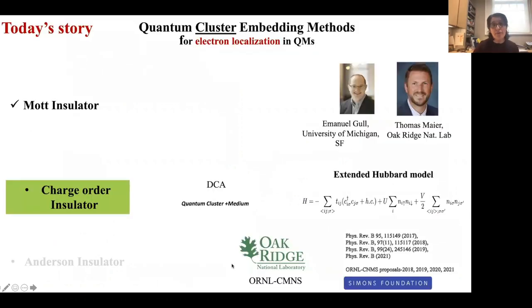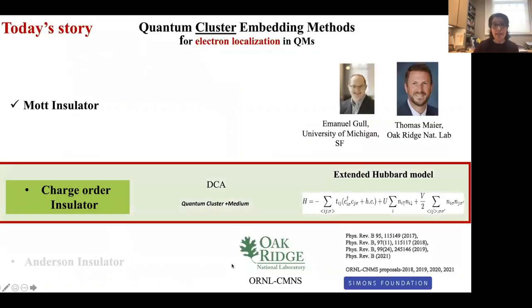Okay, so I have shown you so far Mott insulating behavior and how we can use the dynamical cluster approximation to capture non-local spatial correlation, which seems to be very important for properly capturing the metal insulator transition in certain systems, in particular in the Hubbard model in 2D. Now I would like to go to another type of localization, and this is due to charge ordering. And for this, we're going to consider the extended Hubbard model.